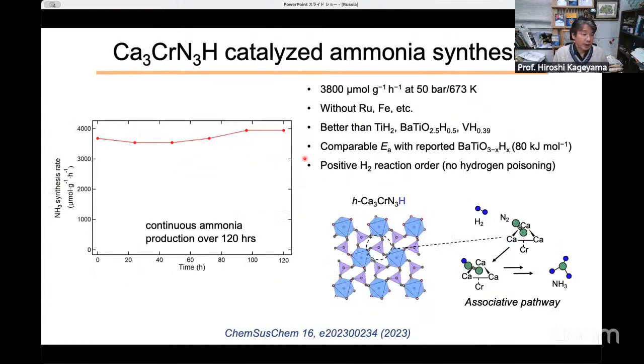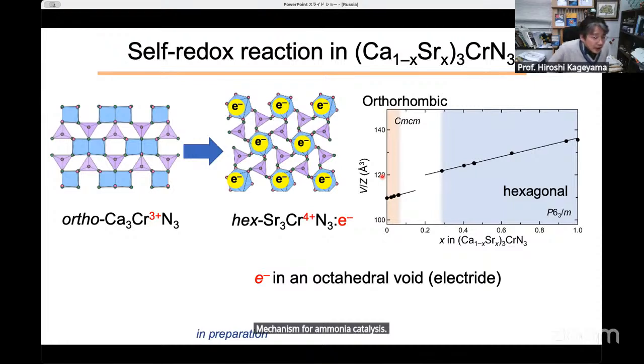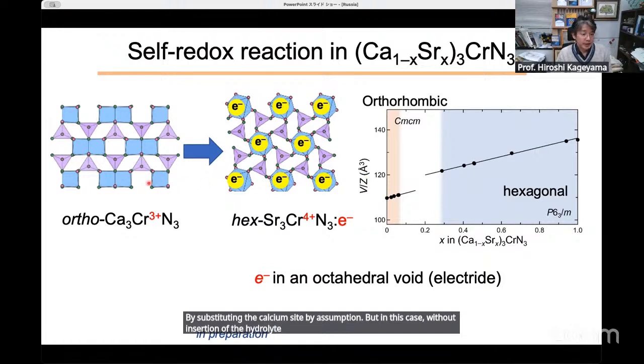Then maybe we may just omit this one, though this shows a nice, interesting mechanism for ammonia catalysis. And my student continued this work by substituting the calcium site by strontium. But in this case, without insertion of the hydride, you are able to switch this orthorhombic structure to hexagonal structure. Okay. Upon 30% doping, this material, without changing composition, is changed into hexagonal structure.